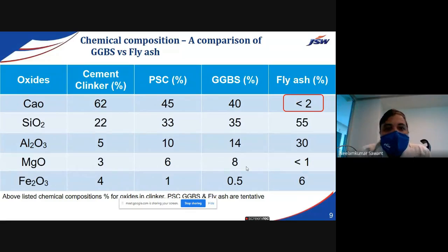The chemical composition, as ma'am Lopamudra told, this GGBS is having calcium more than 90 to 95% in our JSW product. So we will see calcium oxide in a normal cement clinker, 100% OPC, 62% is the CaO, that is calcium oxide, but as far as GGBS is concerned, it is about 40, then silica content is about 35, then aluminum oxide 14%, then the magnesium oxide that is 8%, and ferrous also 0.5%. These are the comparative figures as a table.